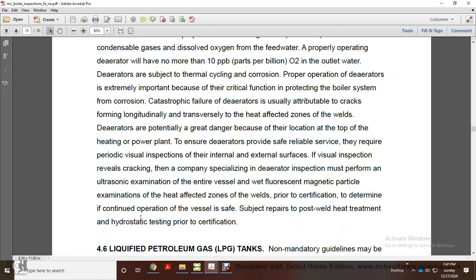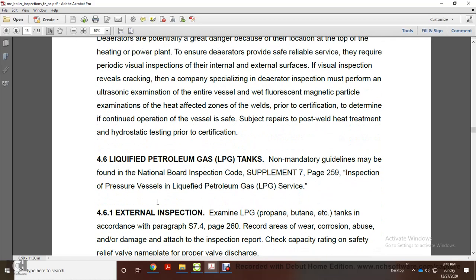To ensure that the de-aerators provide safe, reliable service, perform periodic visual inspection. Internal and external surface visual inspection reveals cracking of the component. Each de-aerator inspection must include ultrasonic examination of the entire vessel, with a fluorescent magnetic particle examination of the heat affected zones, prior to certification to determine the continued safe operation of the vessel. Subject repairs to post-weld heat treatment and hydrostatic testing prior to certification.